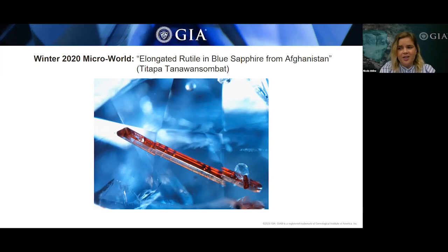And so the author recently examined a 4.24 carat faceted blue sapphire from Afghanistan. The stone contained dusty flake-like inclusions, naturally healed fractures, twinning, colorless apatite crystals, and then this very unusual long prismatic orange crystal that was identified as rutile. And this rutile crystal shape is just not typical for blue sapphires.